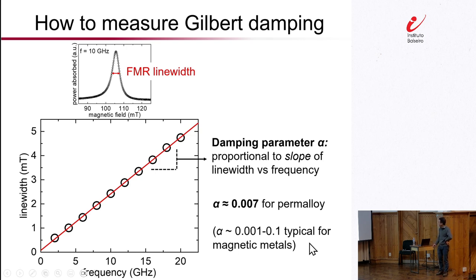Okay, so now I can give you some actual numbers. Some of you might know permalloy. This is an alloy of nickel and iron, very magnetically soft, commonly used in magnetics research. These permalloy films tend to have a damping parameter of about 0.007, but of course, there are many other kinds of magnetic metals out there. You can have a pretty wide variety of different numbers, spanning at least two orders of magnitude, from 0.001 to 0.1 or so.